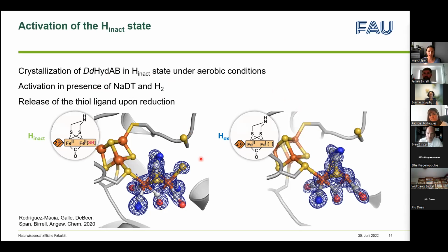And what we could actually see is, so this is the structure that we start off. This is obtained under aerobic condition, and then if we introduce it into the glove box, so we set up the trays right in the glove box, seal them, wait 3 days, and then harvest them in the glove box, we see intermediate states where the ligand partially disappears, and we have some structures where we actually see the electron density completely gone. So in most of the structures that we collect, we see an intermediate where we see low occupancy. So we can determine how much ligand is still left compared to the other atoms in the 2-iron subcluster. But we can also see the ligand fully disappearing in the crystal structure.